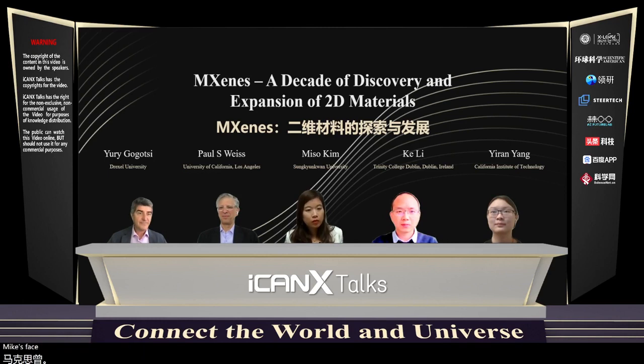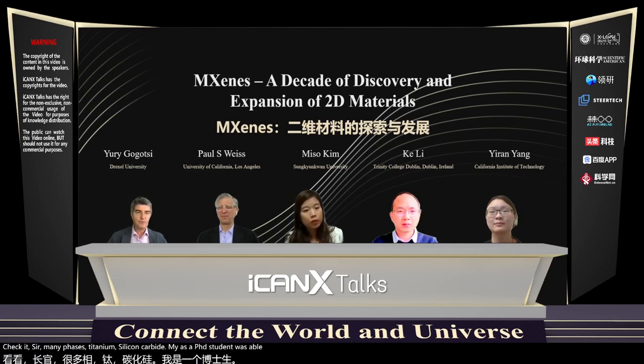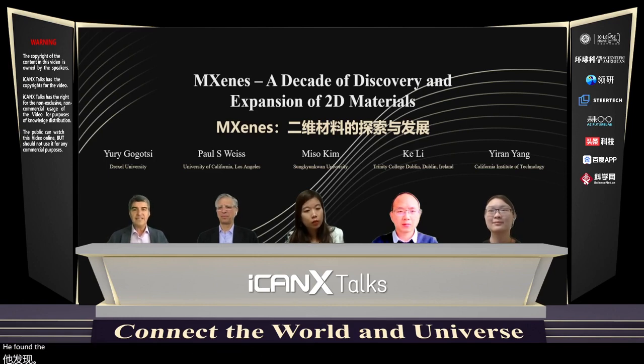MAX phase. And this was again a surprise. He initially checked many phases. Titanium silicon carbide my other PhD student was able to etch just like six years later. He found that titanium 3 aluminum carbide reacted very quickly with HF solution. But when he did analysis after that, he found not titanium 2C, he found titanium 3C2.